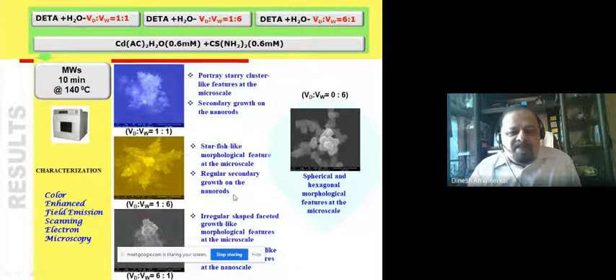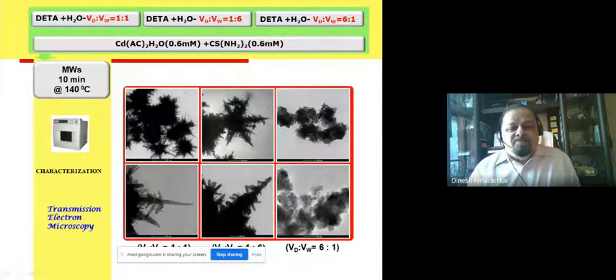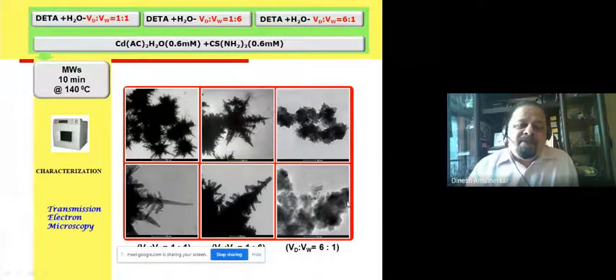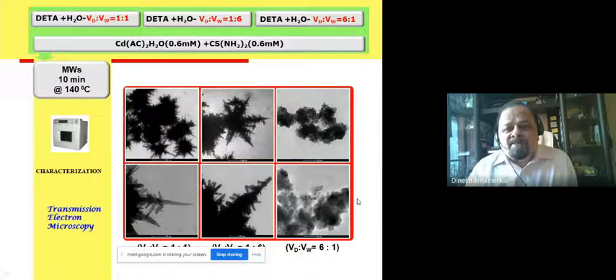We can clearly see the presence of hierarchical buildup, which is much more visible in the FETEM. You can see this is a branch tree kind of morphology. We can see there is a main branch, along with the main branch, there are side branches. These are pine tree kind of structures we can see. Even if we carry out this microwave-induced solvothermal reaction at 140 degrees centigrade instead of 180 degrees centigrade, because we want to make it more green.